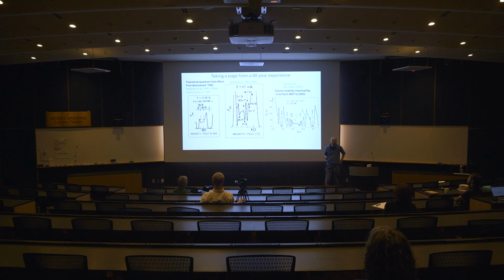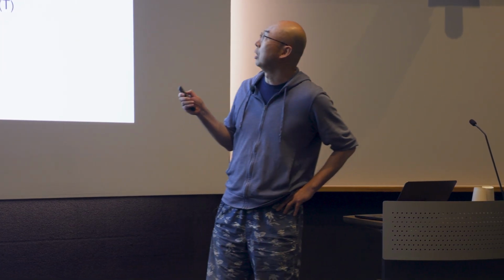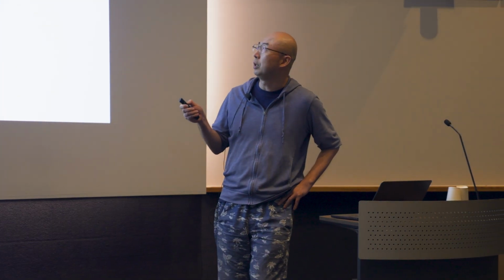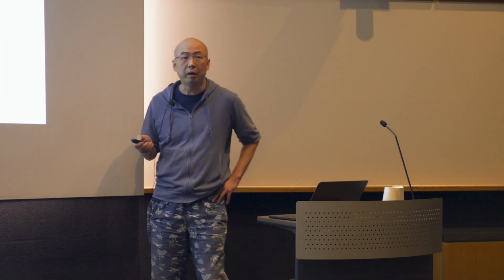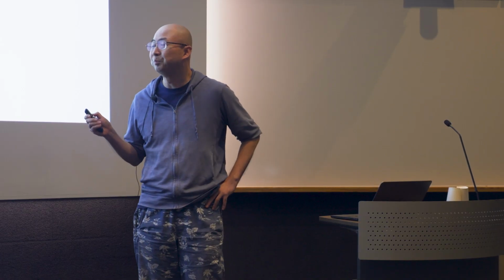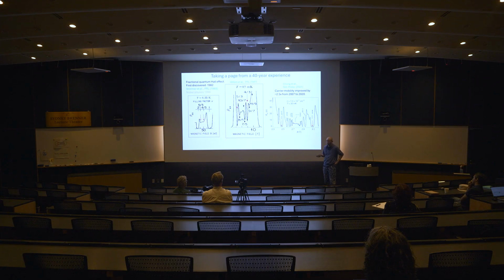This takes about 40 years of development to get cleaner crystals. And especially from 2007 to 2020, they made about a 2.5 times improvement in the mobility. So you think about that, 13 years of life, you only improve by a factor of 2.5. So that is a tremendous amount of effort at Princeton. This group has been working on this for almost 40 years. They were involved in the original work as well.